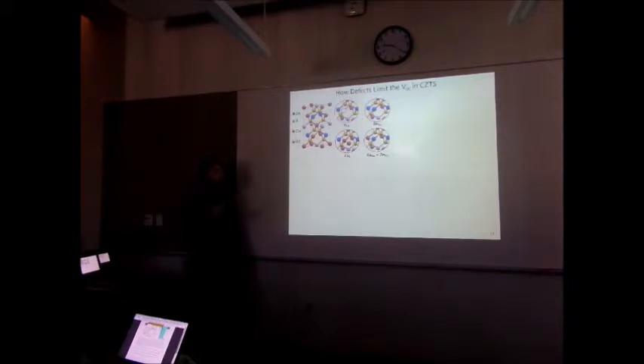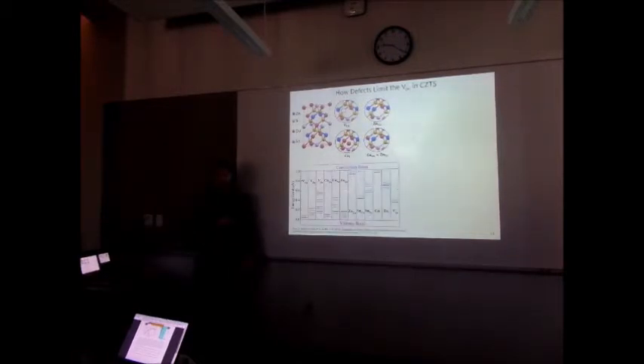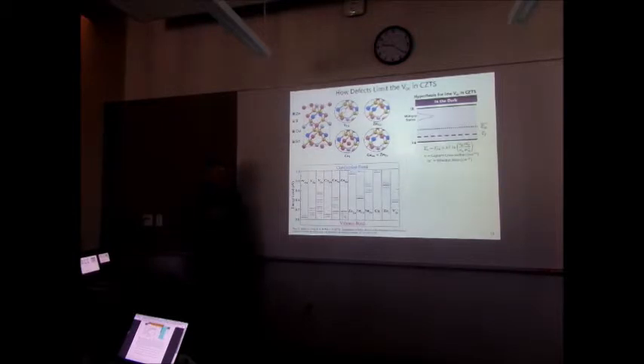So taking a look at the CZTS crystal structure, let's talk about how we can get from this quasi-Fermi level splitting and connect it to defects in a material. So in CZTS, this is the crystalline structure of it. And what can happen, and what does happen in CZTS, is you have these defects that form. You have these copper vacancies and zinc on copper sites and copper interstitials. All these different defects can form, and they can form these mid-gap states in the band gap. And what happens is, when you have this population of mid-gap states in the band gap, and you have this Fermi level, you can also define a demarcation level that denotes when a defect becomes an effective recombination center, and you lose that current, basically.